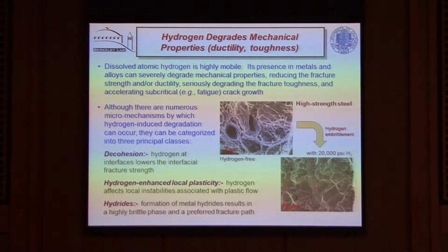So one of the traditional mechanisms of hydrogen embrittlement is associated with decohesion, that hydrogen collects in internal interfaces and leads to a reduction of the fracture strength in those interfaces. This has been particularly difficult to prove, by the way, but is one of the more recognized mechanisms by which hydrogen embrittles materials. It has another effect associated with the fact that it can enhance local plasticity, and this is an effect which was first pioneered at the University of Illinois by Howard Birnbaum and subsequently with Petros Sofronis, leading to local instabilities associated with plastic flow. This is the brittle mechanism, this is the ductile mechanism. Many have felt that it's an either-or situation, but we now believe that these mechanisms actually operate in concert. And of course, in certain materials, hydrogen can form hydrides, and these are particularly brittle phases, which can then fracture. This is a problem in things like zirconium, titanium, and so forth. And this is also a mechanism by which hydrogen can accelerate cracking.